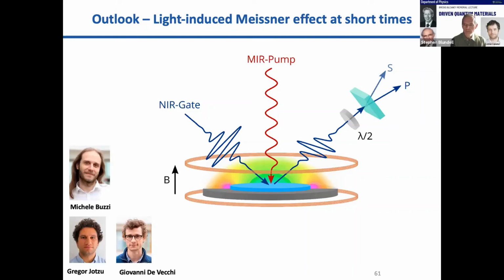The second reason why what Paul says is very interesting is that there are all sorts of proposals in which one could embed these materials in an optical cavity, and enhance the interactions between the laser field and the material in the context of a high Q resonator. Perhaps put yourself in situations in which, for thermal management, you don't need to pump quite so hard, and therefore you could induce this effect better with weaker fields. And there's another 10 reasons why this is a very interesting question, although in the specific case here, it doesn't really apply.